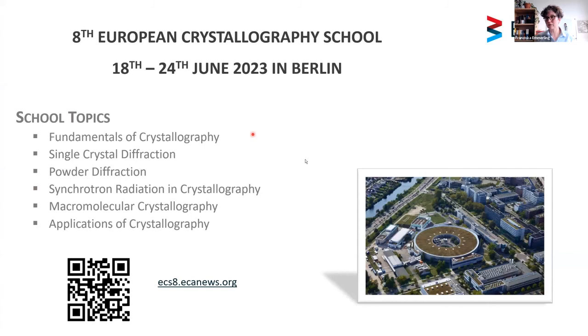The ubiquitous Travis Holman question. Hi, Travis. Great talk. I'm quite curious how one accurately measures particle size by powder diffraction in the face of peak broadening due to sample thickness, position, etc. Yeah. So what we did in these cases, the basis is a Rietveld refinement, and then we have the information from peak broadening, also compared to standard material measured, and so on, and then you can reliably determine the crystallite size of your compound.